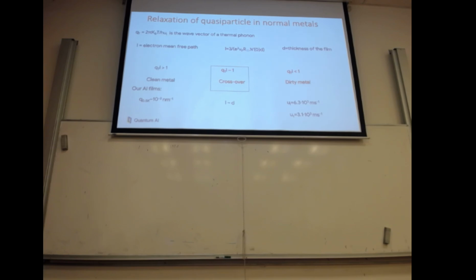An important question is the typical value of the wave vector q of the thermal phonon that we are interested in, because the relation between this wave vector and the electron mean free path tells you how disordered and how dirty you should consider your metal. If you take our aluminium films, you would expect the wave vector at 0.5 K to be about 10 to the minus 2 nanometer to the minus 1. We estimate l to be 100 nanometer, not very precisely, because it seems they forgot to measure the sheet resistance at low temperature, so we don't know exactly what l of our film is. But assuming it is comparable to 100 nanometer, we are in a sort of crossover regime, where the product q times l is more or less equal to 1. So in our film, we are not in the dirty metal limit.